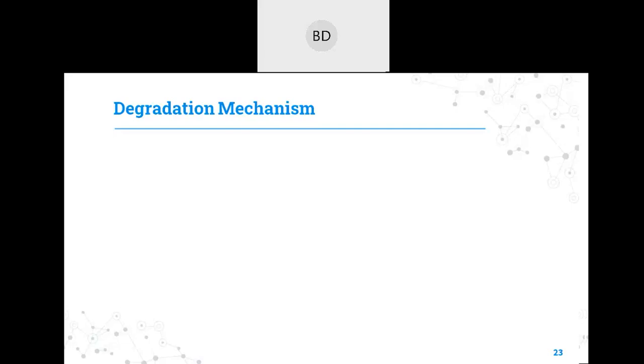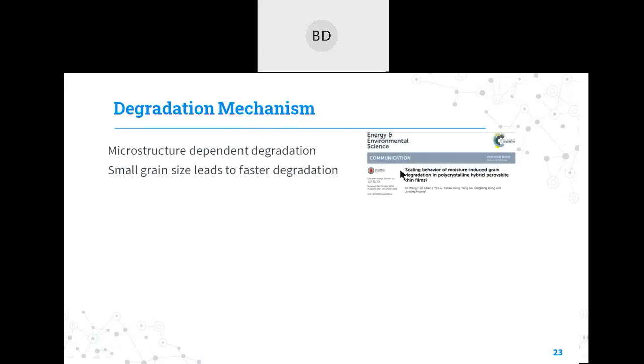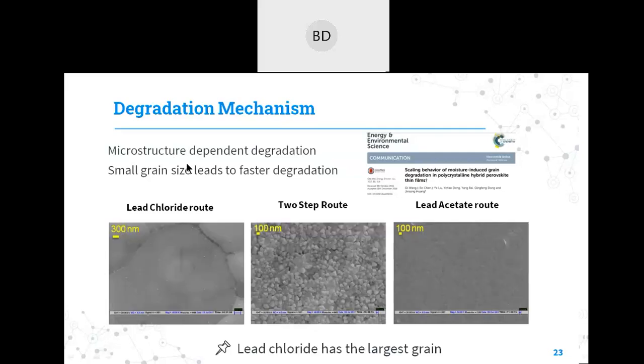To understand this, if you see the literature, it reports that the degradation of perovskite is governed by the size of the perovskite crystals or the grain size of the perovskites. So if you have a smaller grain size, the degradation will be faster. But if you have a large grain size, the degradation will be slower. So to understand this, we have done some scanning electron microscopic images for our films. But what we observed, the result is exactly opposite to this theory.